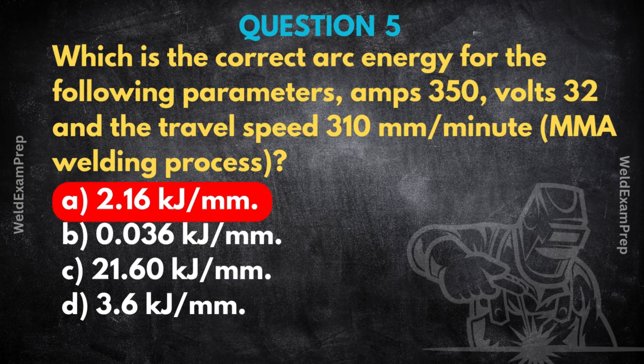Right. And why is knowing this number, this arc energy, so important? It's critical because it directly impacts the cooling rate of the weld, which in turn affects the microstructure, the grain size, and the final mechanical properties like strength and toughness. Too much heat input, things cool slowly, you might get large grains, lower toughness, maybe more distortion. Too little heat input, things cool too fast, you might risk lack of fusion, poor penetration, or even cracking in some materials. It's about finding that right balance specified in the WPS. So this number isn't just academic. It really controls the weld's properties.